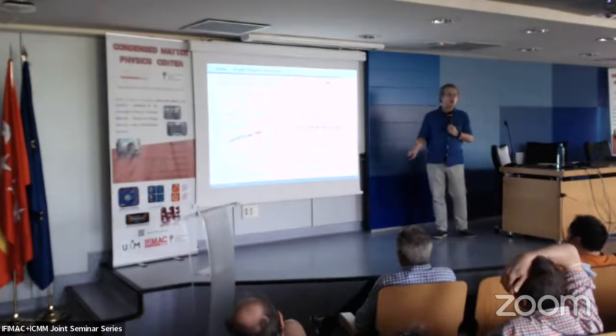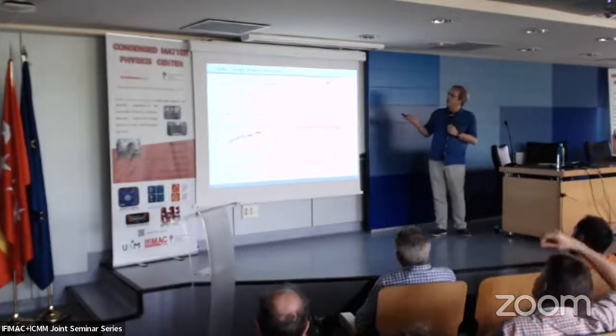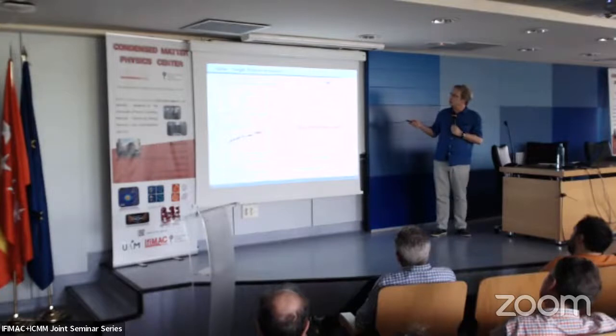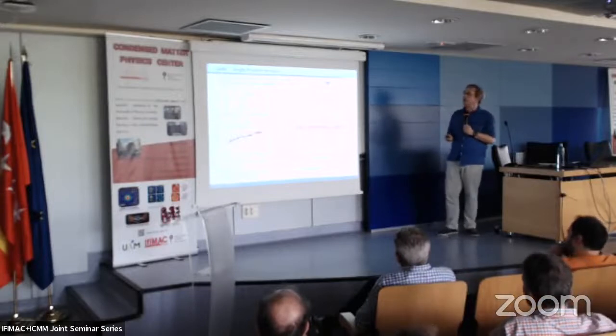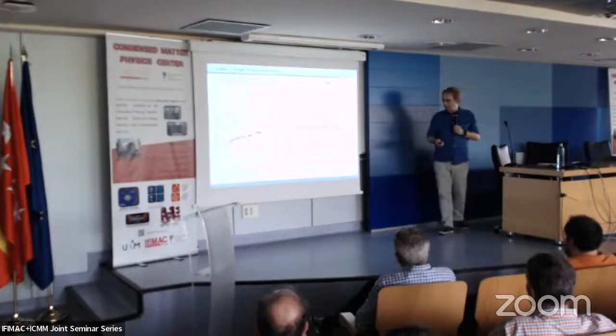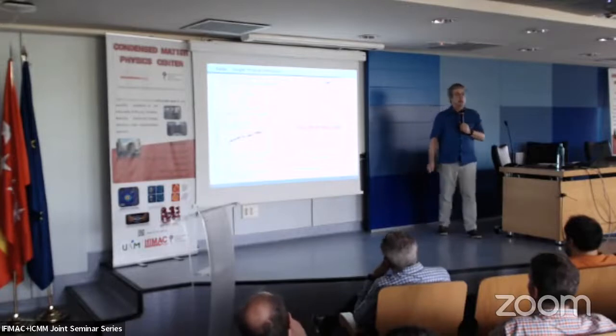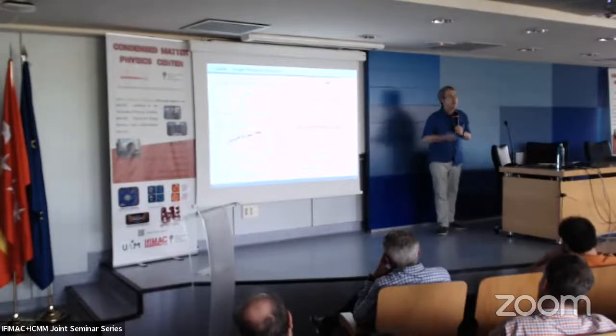This kind of exciton bi-exciton single photon emission has also been observed in tungsten selenide. And so the image of this system is where we have an exciton and the bi-exciton level, which is like a double exciton, so two electrons and two holes confined in a localized spot, and which can be recombined through different polarizations. For applications, this is a very interesting kind of configuration, because if in the system these two levels, which correspond to different recombination paths, which correspond to different polarization, have the same energy, so if they are degenerate, we can entangle these photons emitted.